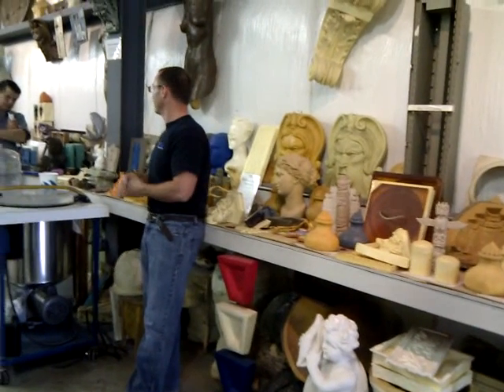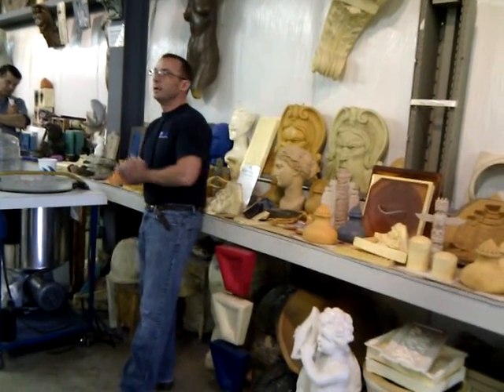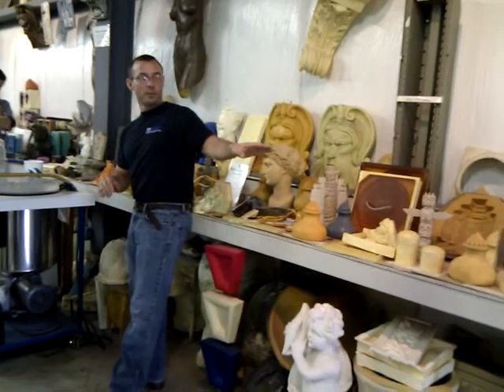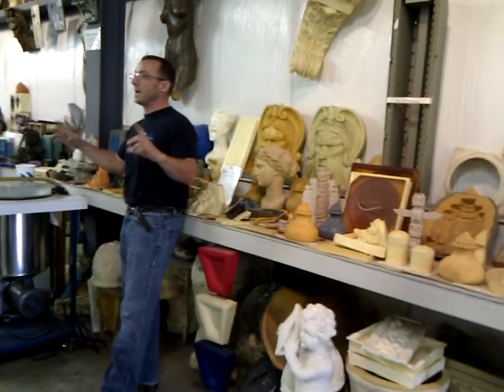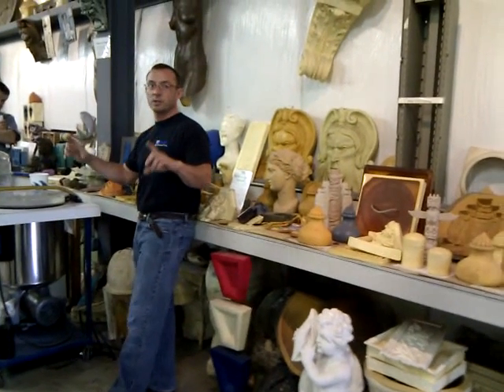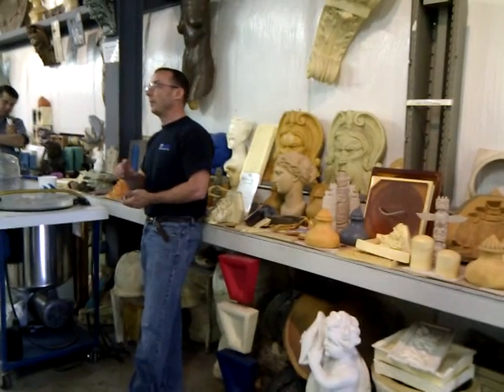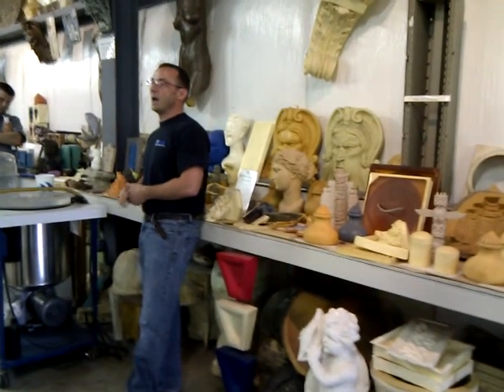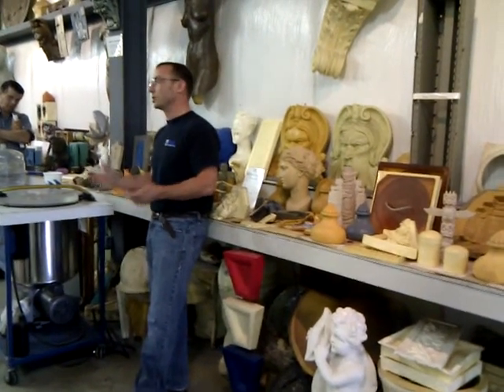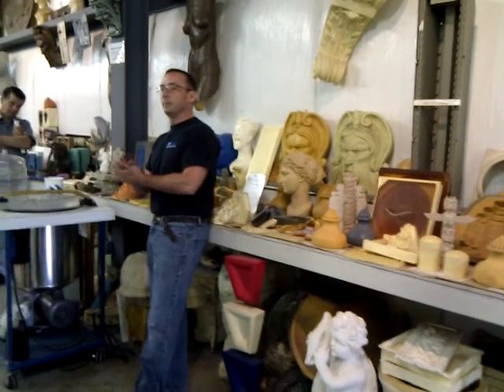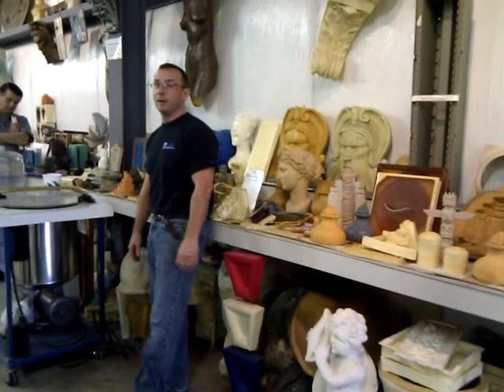But my recommendation would be either with the epoxy, because we had a customer that did bonded bronze with an epoxy to do medallions for highways in Texas, and they had that combination tested in the lab, and they determined that there was really no deterioration over a 10-year cycle for outdoors, so that's why they went with that material.